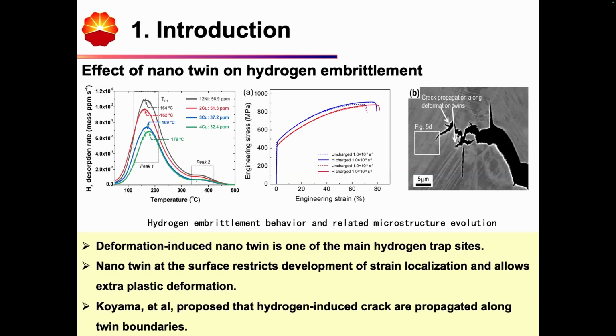Some people also observe ductilization phenomena in the presence of hydrogen. However, since the nanotwins are one of the hydrogen trap sites, hydrogen-induced cracks are also observed to initiate and propagate along the twin boundaries.